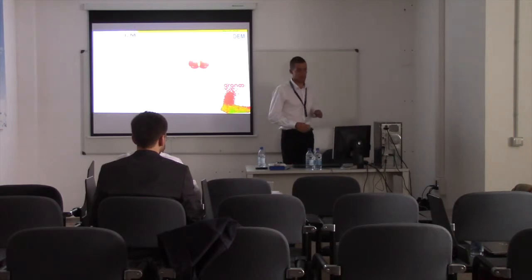We also use a dissipative force, which can be associated to viscous dissipating force between the two discrete elements. So we needed to implement a damping coefficient and critical damping values. And we also implemented the regularized Coulomb law for static and dynamic coefficient between the particles, but also associated to the build platform. And GranOO uses a velocity Verlet algorithm for the explicit time integration schemes.